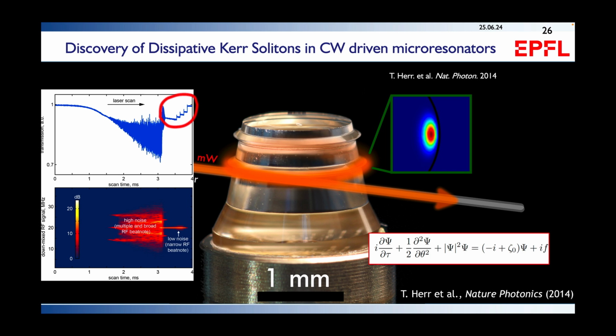And so we discovered this process again about a decade ago. It's a very striking process by which, when you pump a crystalline resonator, shown in this picture, with a continuous wave laser, you find that the resonator itself, when you start pumping it, generates many sidebands. But at some point the waveform inside the resonator becomes chaotic. And when you tune through the zero crossing of the resonator, from the blue to the red detuned side, you see a series of steps. And these steps are commensurate with the resonator starting to form optical solitons.